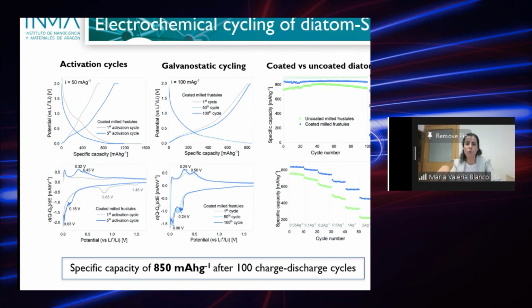But in addition to this, if you see the differences between the coated and the uncoated on the lower part of the figure, you will see that when we make these capacity rate tests, that means that we are changing the current and cycling the anode faster and faster each time, when the material is coated, the capacity is much higher than when the material is uncoated. So this means that, again, it's necessary to do the coating, and in this case, it was quite good. So one of the most important results of this part is that we were able to reach a capacity of 850 milliamp hours per gram after 100 cycles of charge and discharge, and the capacity was quite stable. So I think this is one of the key results.